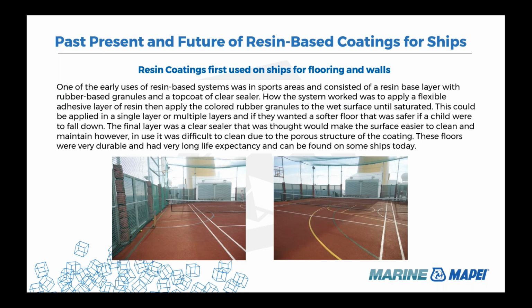The final layer was a clear sealer that was thought would make the surface easier to clean and maintain. However, in use, it was still difficult to clean due to the porous structure of the coating. One good thing about the floors was that they were very durable and had very long life cycles. They can still be found on some ships today, either exposed or under newer decking systems that have been laid over the top.